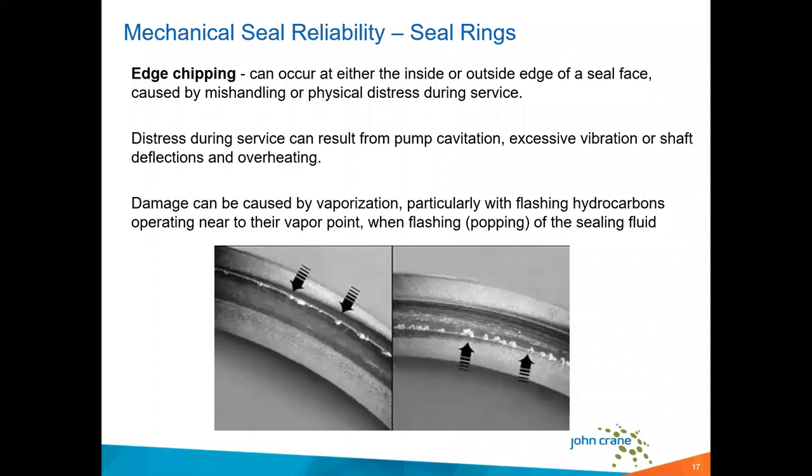Some examples here of edge chipping, and these would be the areas we would look at in terms of clues as to what occurred or what's potentially contributing to the reduced performance of the seal. So the edge chipping can occur either at the inside or outside edge of the seal face, usually caused by some kind of physical distress during service. The distress during service can result from cavitation, vibration, shaft deflections, or overheating and vaporization of the fluid,